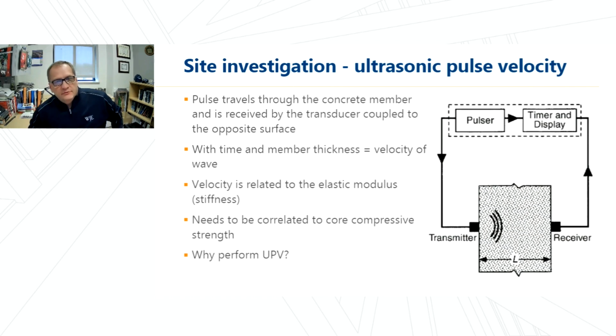So we also did ultrasonic pulse velocity on the double T's. And we do this by sending a pulse through the concrete member, which is received by a transducer on the other side of the concrete element. And if we have the member thickness and the time that it takes for the pulse to go through the member, we get the velocity. And that can be related to the stiffness or the elastic modulus of the concrete. This particular method needs to be correlated to the core compressive strength, which we did. We'll talk about it in the next slide.